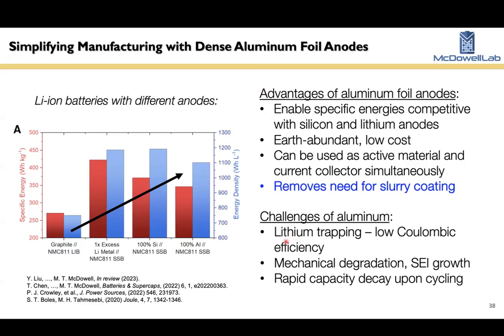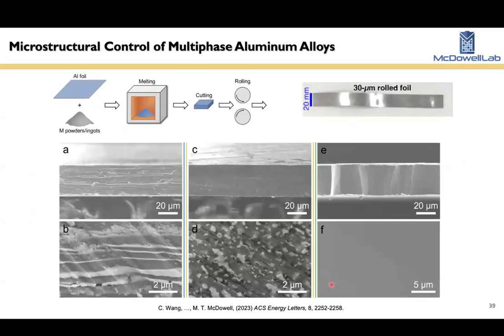There's major SEI problems in liquids, but I'll show you in a second, we can overcome this in solid-state batteries. Beyond that, there's issues with mechanical degradation and trapping of lithium within the structure and the material itself. So we've been working on how to develop materials and composite microstructures that can overcome these issues. So in my group, we've been doing a lot of metallurgy recently, actually. We have equipment where we can do small-scale cold rolling and make all sorts of different alloys of materials.